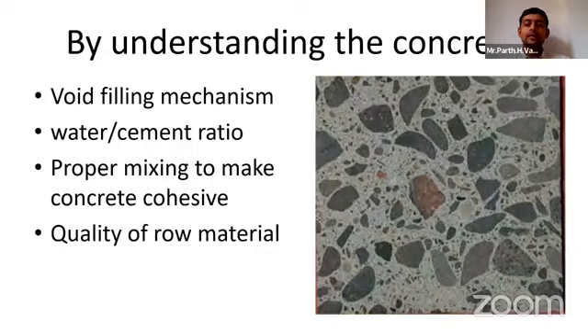So 20 mm aggregates are there in one bucket, then some voids are also there. Those voids are filled by 10 mm aggregates, and voids of 10 mm aggregates are filled with sand. Voids of sand are filled with cement, and voids of cement are generally filled with water when we make concrete. But after cement settlement, those voids are also filled by the cement process. So at the end, we have very few voids. In case of Portland Pozzolana cement, meaning PPC cement, fly ash is also available, which fills those voids properly and gives better strength results.